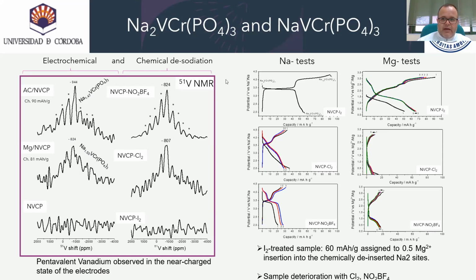Sodium and magnesium test cells are assembled with this de-sodiated sample. The left part, the middle part. For the iodine treated sample, the profile agrees with the expected insertion of sodium ions into chemically de-inserted sodium 2 sites and vanadium 4+, vanadium 3+ reduction at 3.4 volts. In the right part, a quasi-plateau at around 1.2, 1.3 volts on this chart is assigned to the insertion of 0.5 magnesium ions.